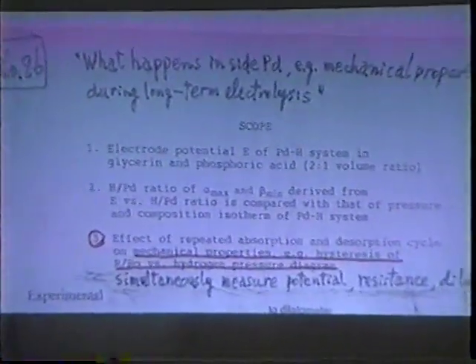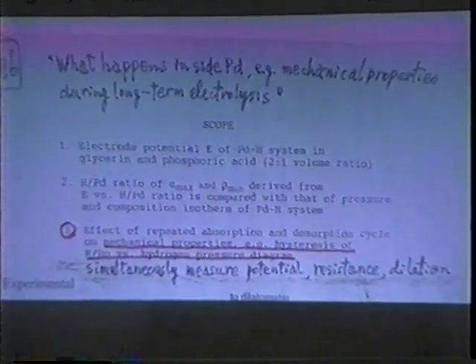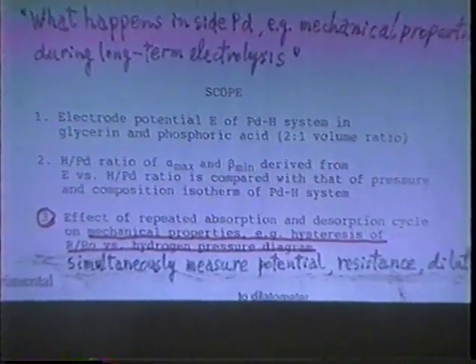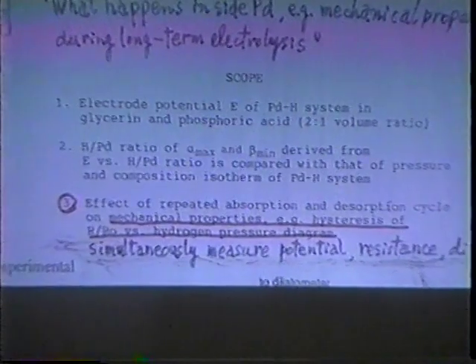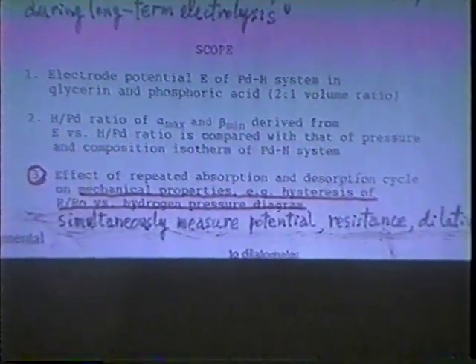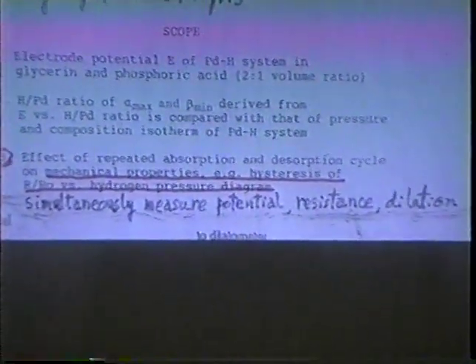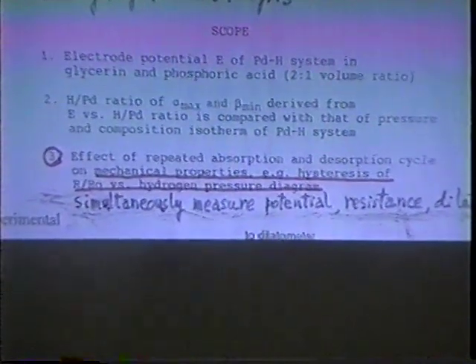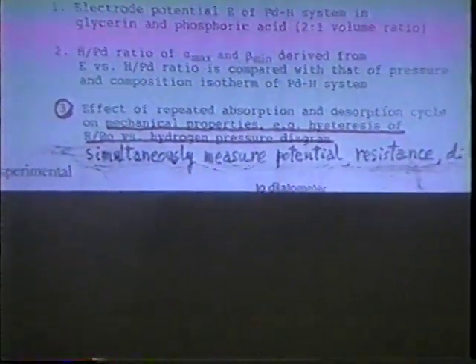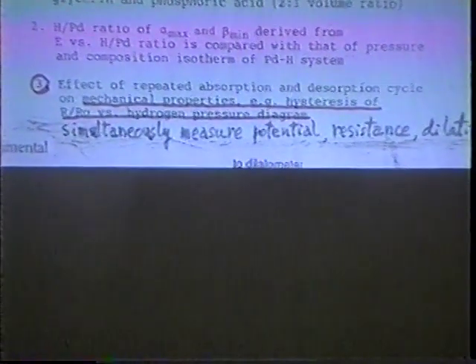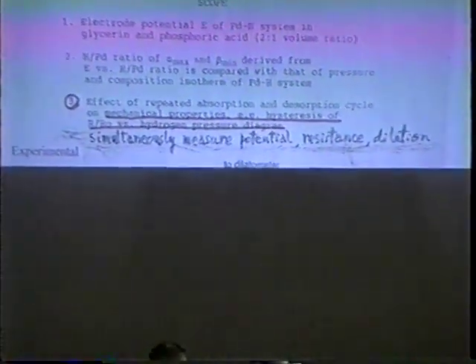Our point is what happens inside Pd, for example, mechanical properties during long-term electrolysis. To simulate this situation, we use the repeated adsorption and desorption cycle by electrical cathodizing and anodizing. And simultaneously, we measure the potential of electrode and also resistance and also dilation. And we evaluate, for example, mechanical properties by hysteresis of R over R0 versus hydrogen pressure diagram.